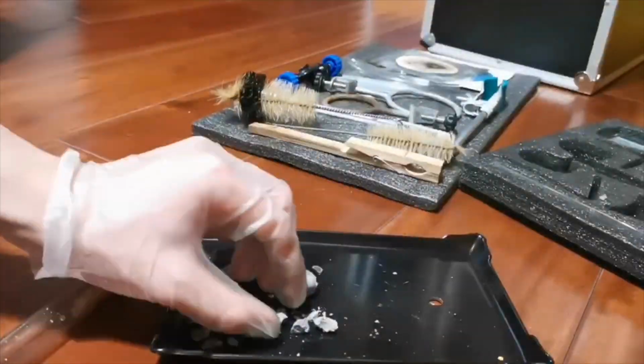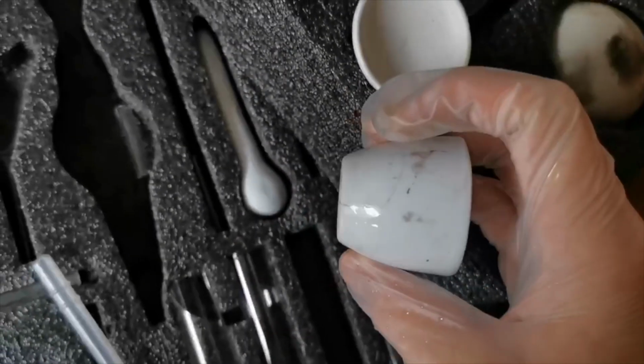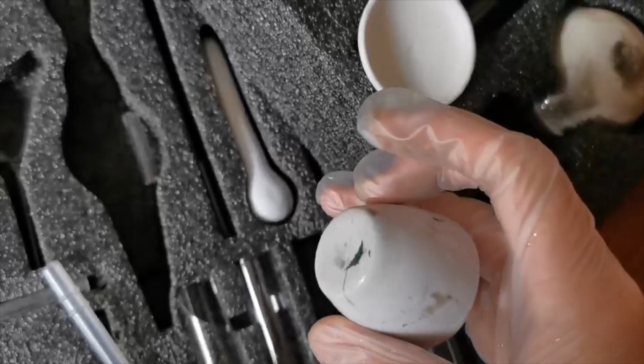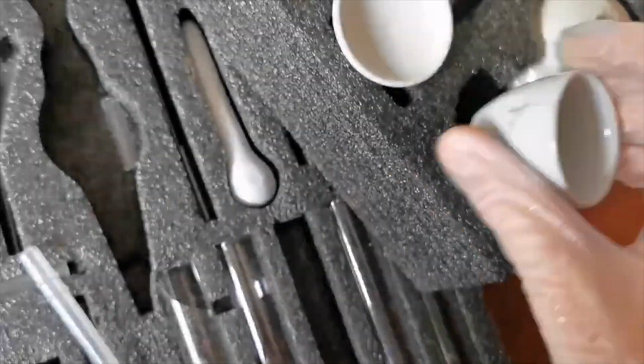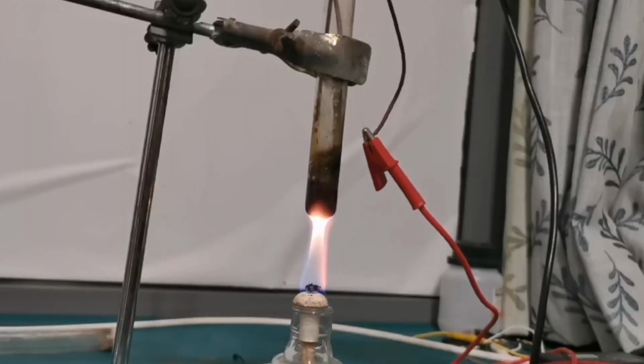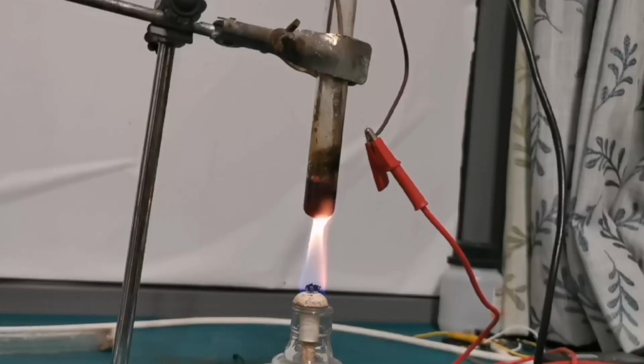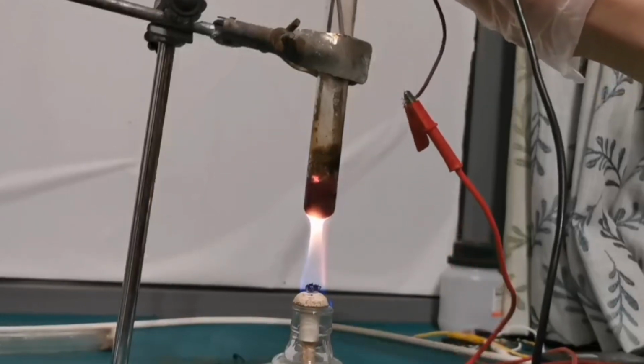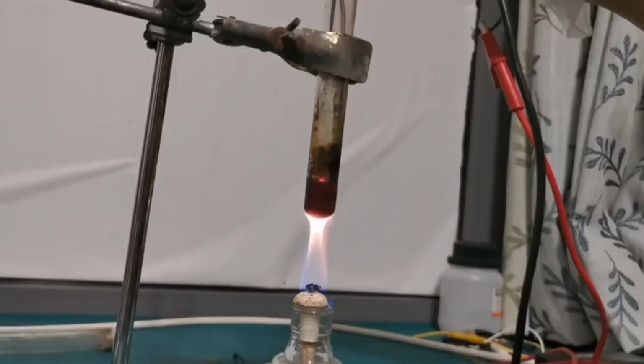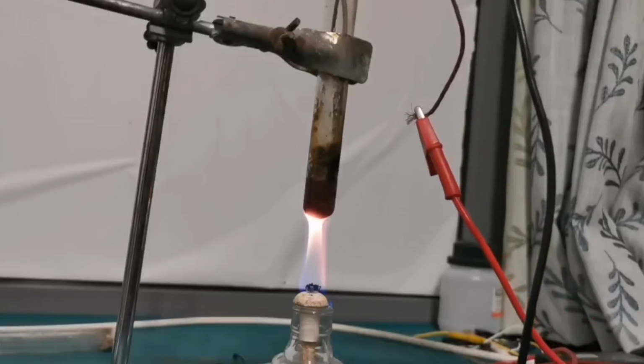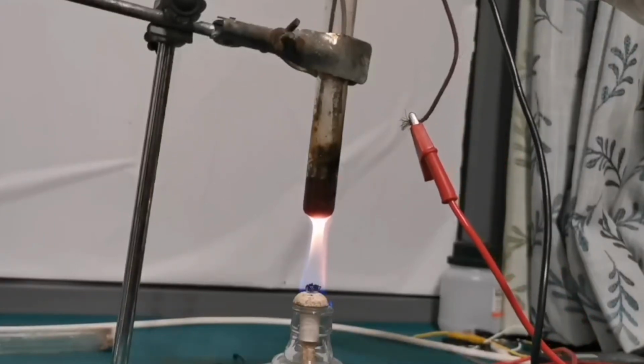Also, I noticed that the process keeps destroying my stuff. The ceramic crucible produced a lot of cracks when it cools, and so do my test tubes. This problem can't be easily solved, and the only practical solutions are to either keep the electrolysis going for a very long time and produce a lot of lithium in one single run to compensate for the loss of the crucible, or instead to do the electrolysis in a metal container.